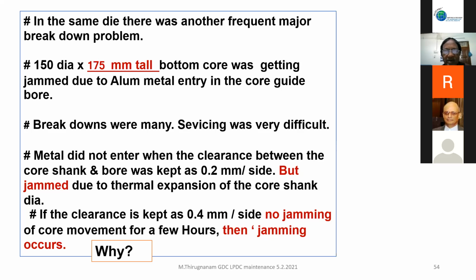But the core jammed due to the thermal expansion of the core shank. Again, the problem. There was no metal entry, but it jams for a different reason. First, it was jamming by metal entry. The second is lack of clearance. So, totally different. Then, if the clearance is kept at 0.4, within about a day, metal enters. So, how to solve the problem?